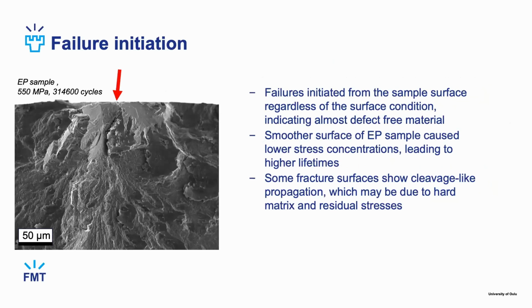Yes, and in our case, we could see from the fracture surface that we studied that we were able to print quite dense material, because all of the initiations were from the surface, regardless of this surface condition. The as-built structures fractured from the surface, but also these electropolished ones. And the crack propagation seems to be quite cleavage type in the beginning before the propagation rates. Of course, this smoother surface caused lower stress concentrations for the geometry factor, and that led to higher lifetimes.